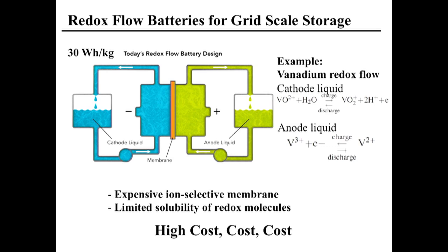However, it's the cost. Vanadium's cost. You need this ion conducting membrane to be low cost. Nafion is the one used right now, produced by DuPont. High cost. And you have two liquids flowing with a very thin membrane. If your pressure is not balanced, your membrane is broken, and then you need to go in to fix it. High maintenance. And also, the solubility of this molecule is not that high. It's about 1.5 molar only.